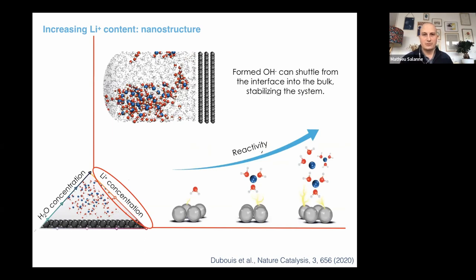And so in that case, what you observe is that you form this kind of nano bubbles that can come close to the electrode. And so our interpretation of this effect was that now, due to this increase of salt and to the presence of large domains, once the water has reacted, you can have some proton transfer reactions that occur within the domain. And so it will tend to stabilize the product and to not allow the reformation of the water molecules at the surface.